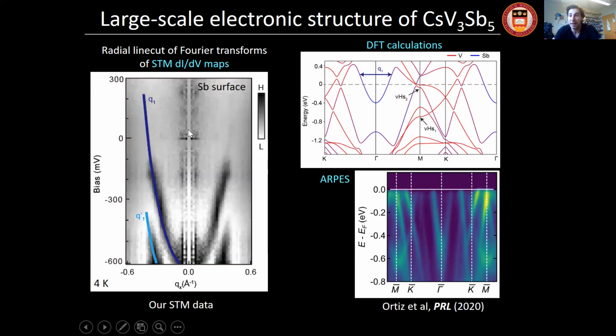And the complete data set looks like this. These are very low wave vectors that you see here. And if you compare what it can actually match, it beautifully matches this gamma pocket here. So this is an antimony pocket that we can see that also matches ARPES fairly well.